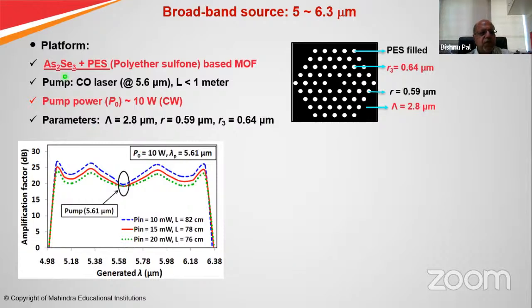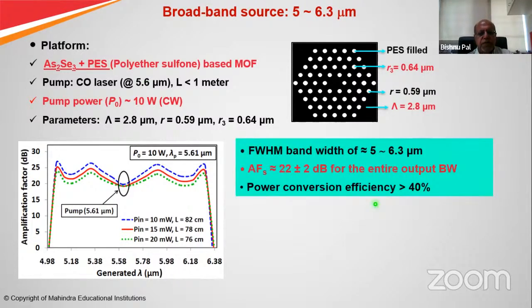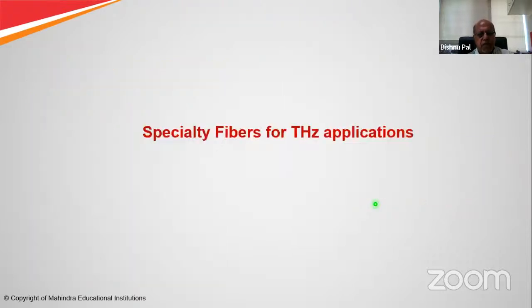When it is pumped with a commercial carbon monoxide laser at 5.6 micrometer, within a length of 1 meter, we could get a power conversion efficiency of almost 40% for 5 to 6.3 micrometer.